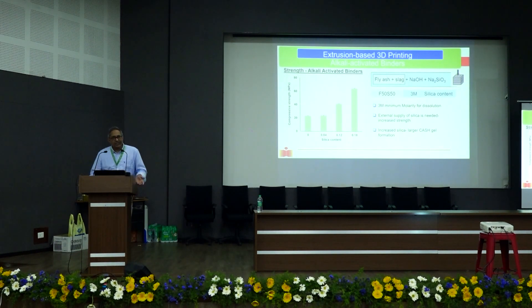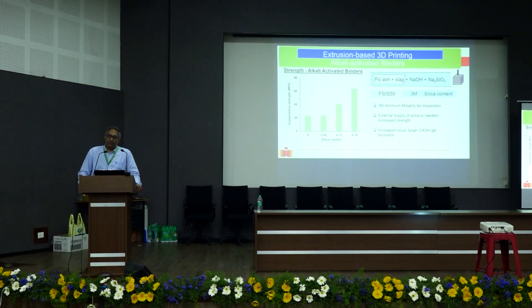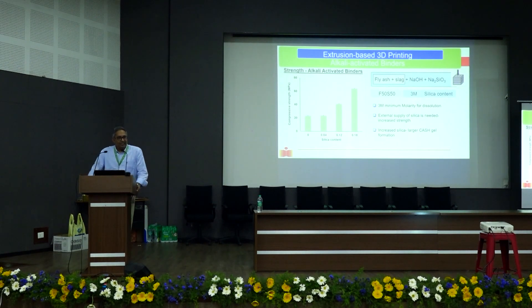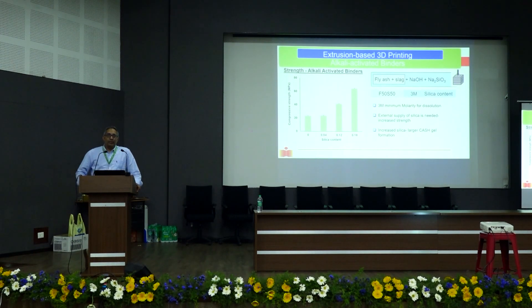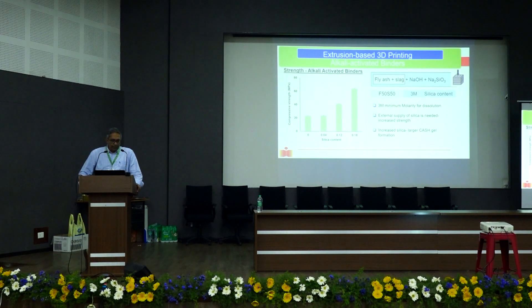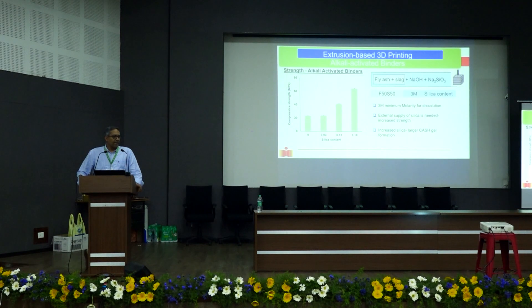We took on the challenge of developing 3D printable alkali-activated binders — not dealing with cements, but printing with alkali-activated materials. The material we chose is fly ash and slag with sodium hydroxide and sodium silicate. Sodium silicate is an external source of silica. The graph shows what happens to compressive strength if you keep increasing the dose of external silica: if I increase external silica, I gain in strength. I want more strength, I dope more silica into my activating solution.